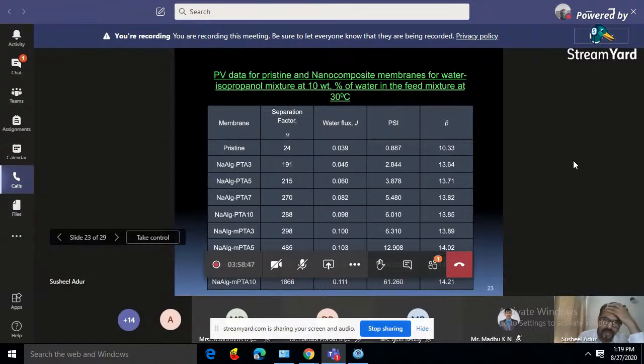Then I started using NaAlg PTA3, PTA5, PTA7, and PTA10. I see that the performance increased when I added PTA. Further, when I added MPTA, the performance further increased and it went up to 1866 for MPTA 10. So if I compare MPTA 10 and PTA 10, PTA 10 is 288 only, and MPTA 10 is 1866 for separation factor. So it clearly shows that modification has value.